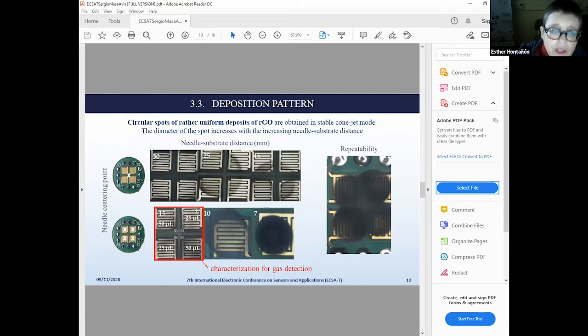So we moved to another type of experiment in which the needle was centered and pointing to the center of the individual sensors. In this one, you can see that the distance is the same, but in the first one the needle was pointing to the center of the substrate, and in this way we performed the position test, centering at any of those. And in this case, there was some overlapping of the deposit, so that's the reason why it's not fully uniform. But when you reduce this distance further, you can see that the size of the spot approaches the size of the interdigitated electrodes, and you can get even smaller.